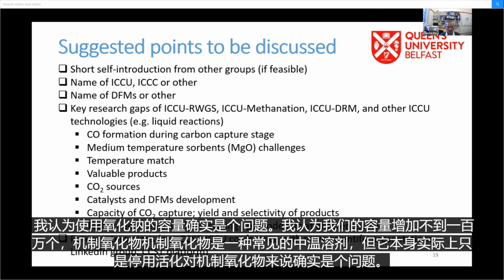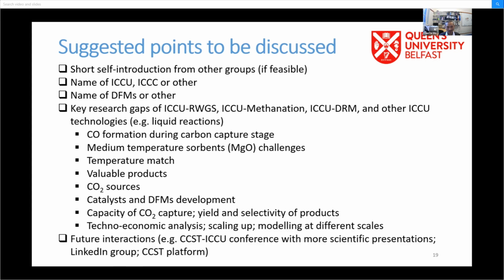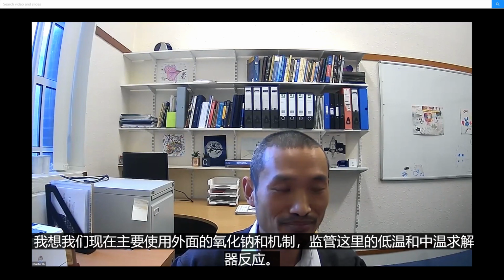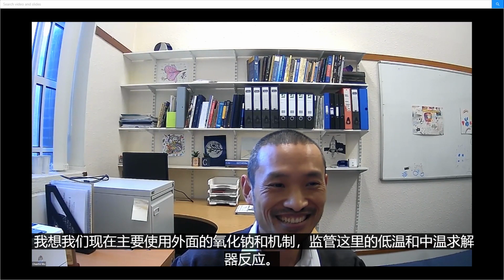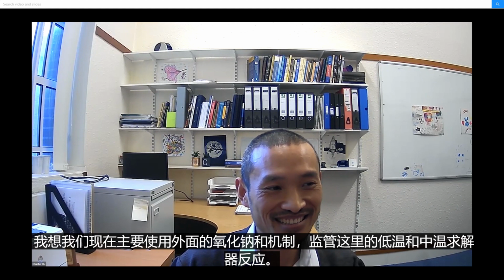And magnesium oxide is a common intermediate medium temperature solvent, but deactivation is really a problem for magnesium oxide. I think for high temperature, calcium oxide will solve most of the issues. That's fine. It's just the low temperature and medium temperature solvents, in terms of the capacity. We mainly use sodium oxide and magnesium oxide at the moment for low temperature and medium temperature reactions here.